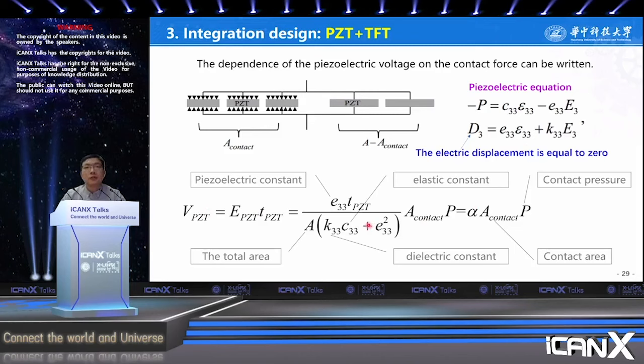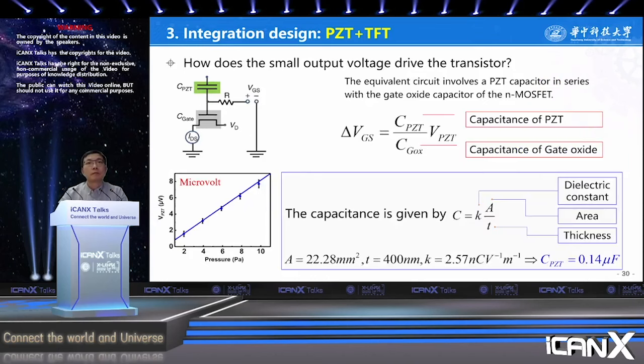We know that the electric field strength E multiplied by the thickness of the PZT equals the voltage. The field strength multiplied by the thickness of the PZT is equal to the output voltage. From the function, we can find that it is determined by the thickness and the area of the PZT, the piezoelectric constants, the contact area and the applied loading. The modulation of the gate bias with applied pressure is related to the PZT.